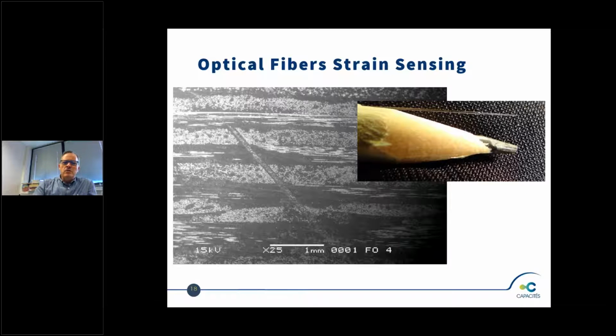Now I'm turning towards optical fiber strain sensing. So this strain sensing comes from, you see the pen there, the pencil, and you see the optical fiber, which is a tiny glassy stick, and the sensitive part is like 10 microns inside the glass coating of the optical fiber, which is 125 microns. And in addition, you have a plastic coating, and the final diameter is 250 microns. And on this graph, you see a line at 45 degrees from the horizontal, and this is the optical fiber